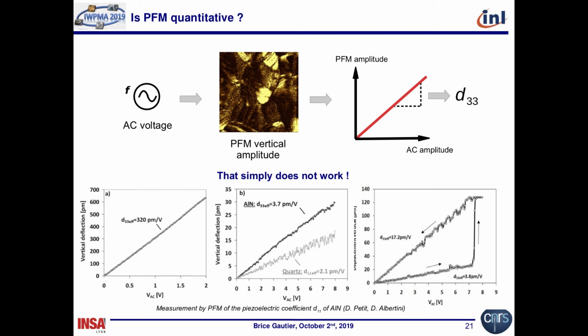In the three cases there, this is exactly the same sample. And from this try there, you have 3.7 picometers per volt. From this one, you have 17.2 picometers per volt. And this one is 320 picometers per volt. It's the same sample. Okay, tell me the value that you want. I will find it.